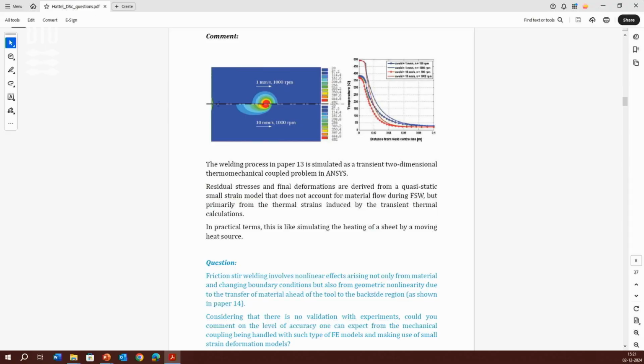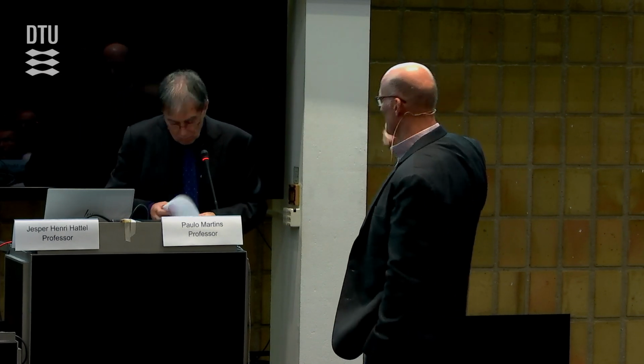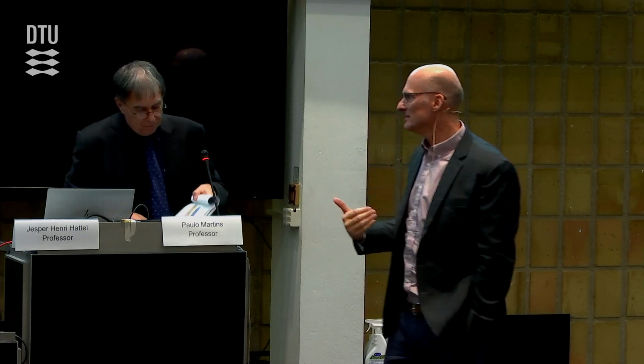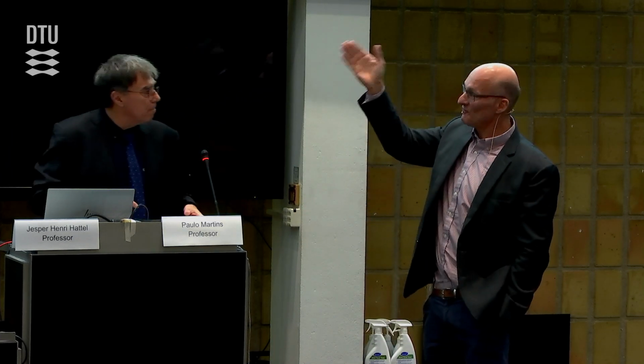It's the heat source that we derived based on the analytical solution with experimental observations from an experiment with either the force or in the other case the fully analytical. So it was not a Gaussian. No. So this was actually the heat source that we derived in previous papers. Yes. So, of course, relevant for friction stir welding.